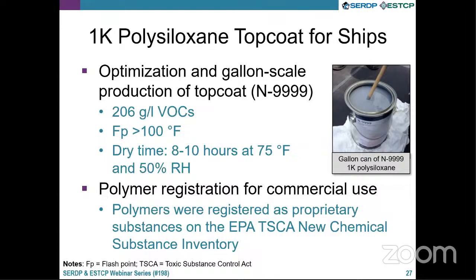We had to make sure the consistency—there were consistencies with producing the polymer, the order of addition with the reagents and components in the coating. But eventually we had settled on a formula which we deemed N-9999, and that formula had a VOC of 206 gram per liter, a flash point of 100 F, which NAVC coatings are required to have a flash point above 100, and then a dry time of 8 to 10 hours at these laboratory conditions.